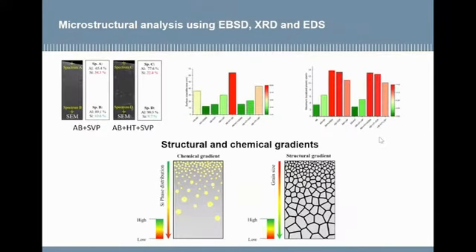treatments. Interestingly, the mechanical surface treatment resulted in a structural and also chemical gradient in our structure. So structural in terms of grain refinement on the surface, and was gradually increasing as we are going to the core of the material.